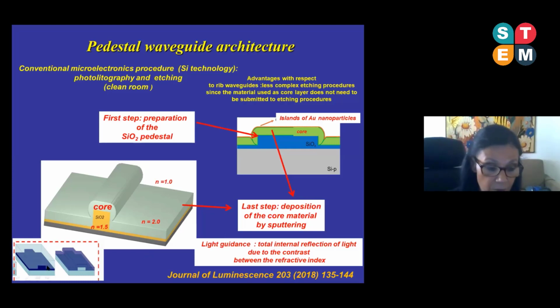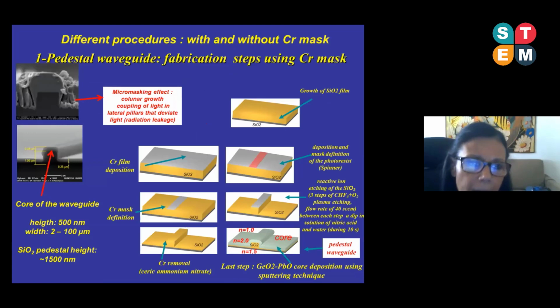In that case, we have to etch the material of the core, and this is not an easy task, mainly when we deal with heavy metal oxide materials, as is our case. So, the pedestal platform represents an interesting alternative because we prepare the pedestal waveguide and then we deposit over it any material we want, and we do not have to etch the material of the core.